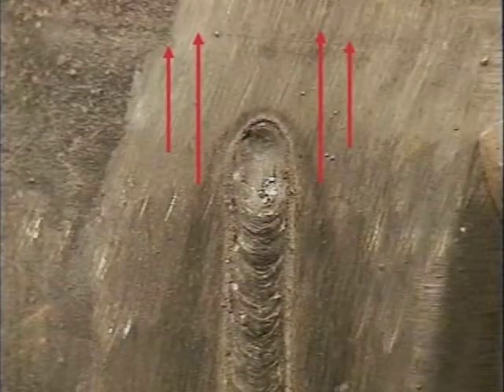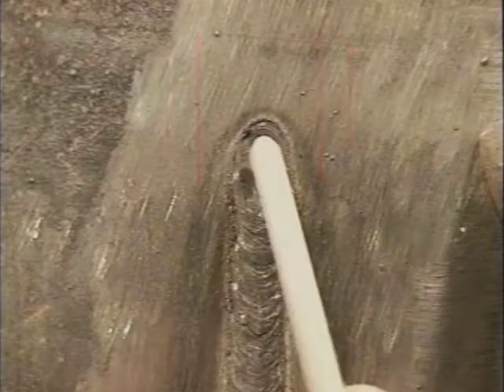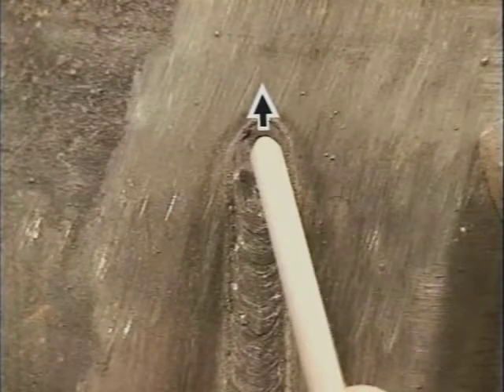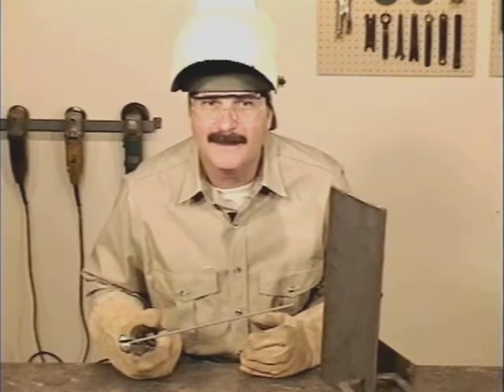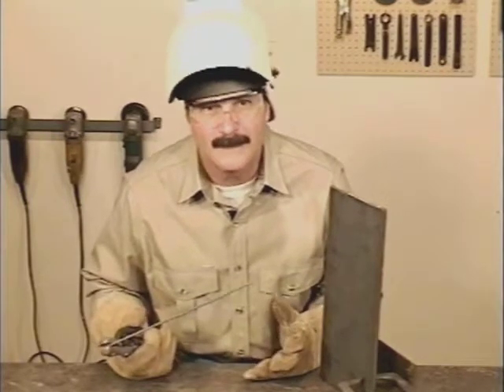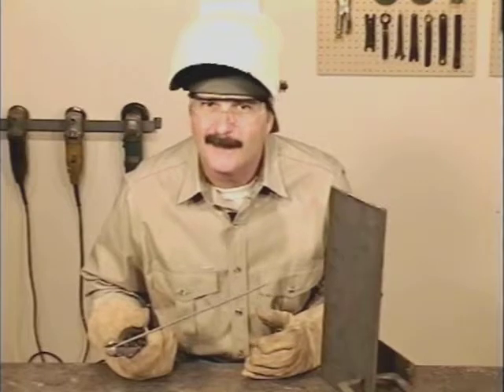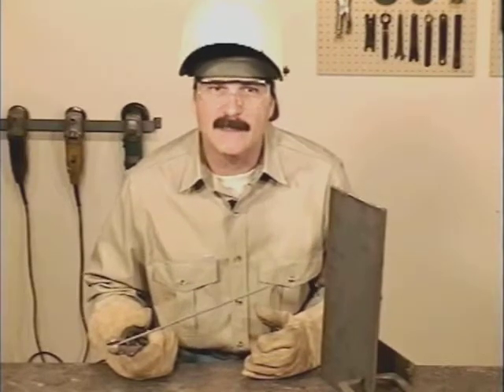When you weld uphill, you'll be welding into the heated metal, so turn the amperage down a little. Angle the rod up so the force of the arc doesn't blow the puddle out. An uphill weld really gouges into the base metal, making undercutting a potential problem. So pay particular attention to the sides of the puddle and watch the weld buildup underneath the rod. If the base metal gets too hot, the puddle may fall out, or you might burn a hole right through the metal. Mess with the amperage setting and your travel speed until you can carry that puddle right uphill.